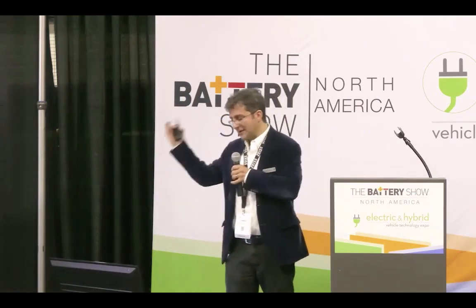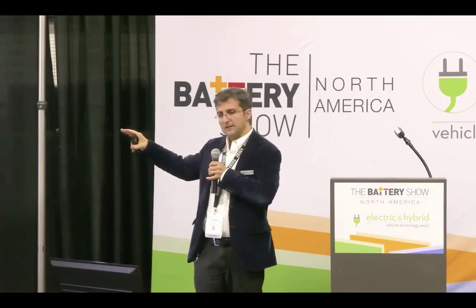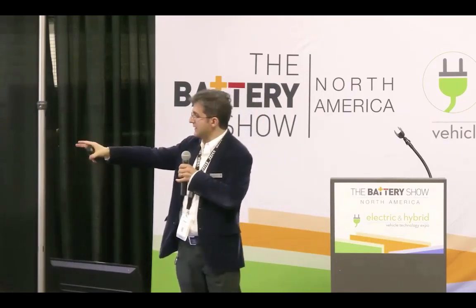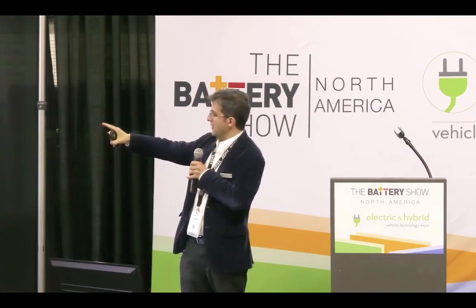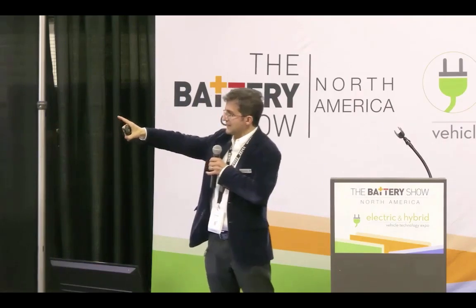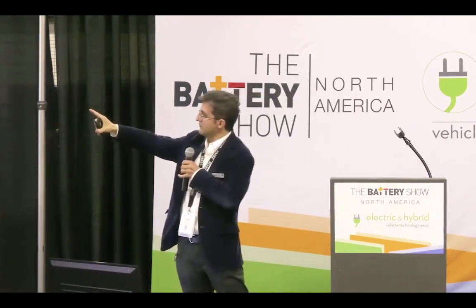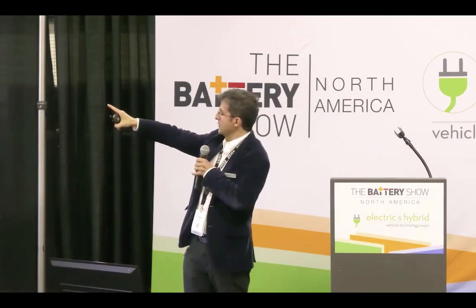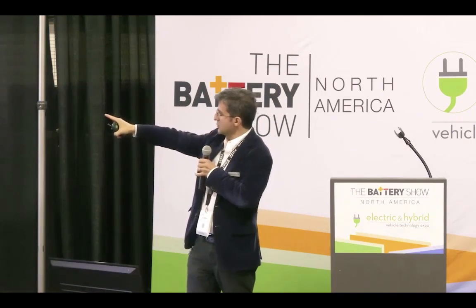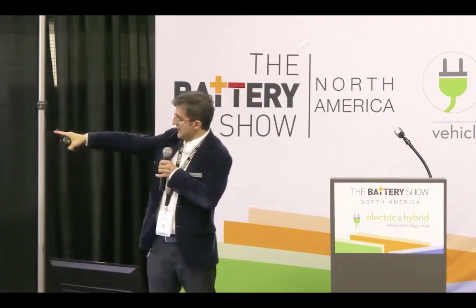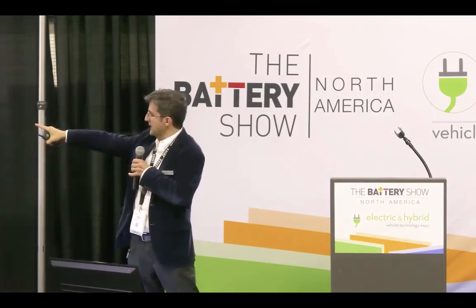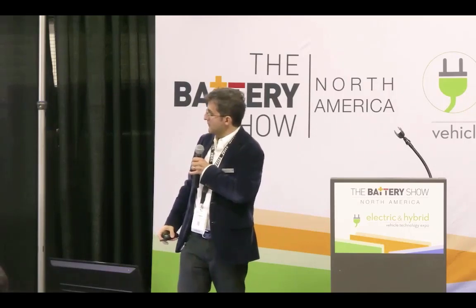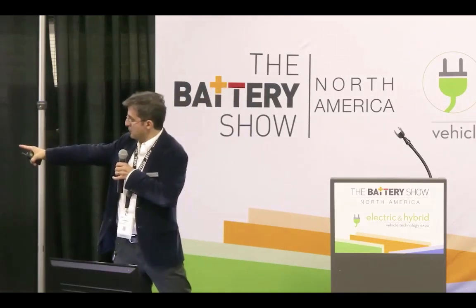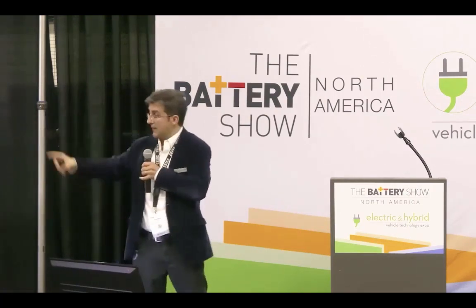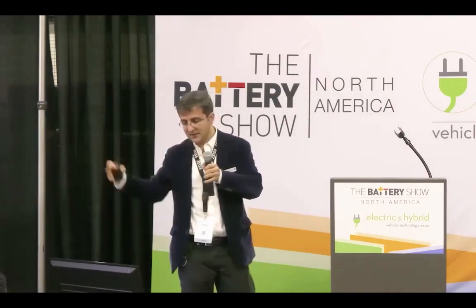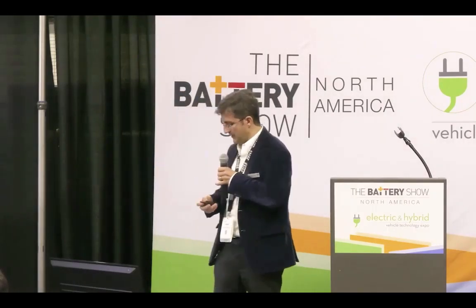I could give you more and more examples, but in reality, what I would prefer is to refer you to some of the publications that are out there. This is a Nature Communications publication of 2020, in which you can see how you can scan with X-ray CT with 23 micrometers voxel size, and then go all the way to the ultra X-ray microscope at 126 or even 63 nanometers, and see details that are quite similar to an SEM, or scanning electron microscope. This one is only for comparison, but in reality you have the data in the X-ray CT with 3D data. So you can actually see through the full section of the battery that you are scanning.